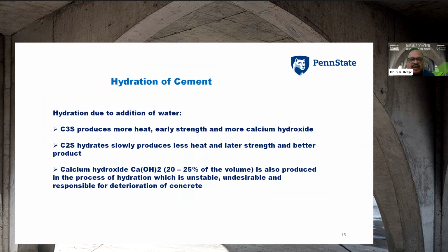And if you add water to the cement, it will start hydrating, and C3S will react with water. It forms CSH gel. Similarly, C2S and C3A; I will show the reactions in the next slide. Calcium hydroxide also comes out of the hydration process, but it is unstable and undesirable, because the more calcium hydroxide, it is just like high blood sugar in the human body. So for cement, high calcium hydroxide is just like diabetes.